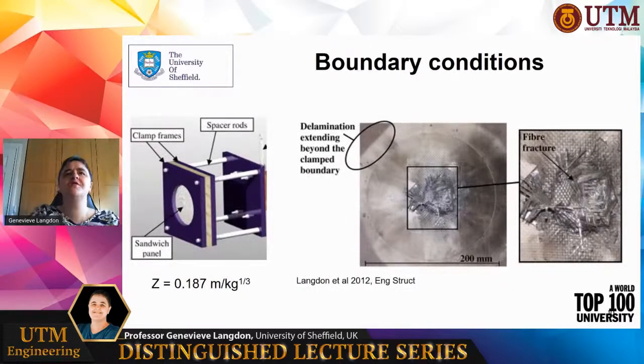The boundary conditions for fiber reinforced composites in blast tests have a big influence on the response. If you clamp a material like this too tight in a square frame, then the panel will start to indent into the frame, and that will cause a premature and unrealistic failure mode at the edges. So one of the things we can do is change the boundary conditions to prevent this.